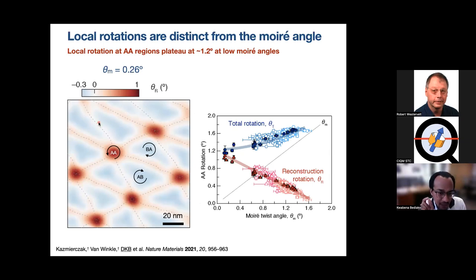But why does the rate plateau as you go below 1.5? Well, it turns out that we know that because of relaxation, the total rotation, if you were to put blinders on and only look at the rotation at an AA site, you would see from our measurements that the total rotation basically plateaus off. So even though the Moiré twist is 0.26 degrees, locally at an AA site, it looks like 1.2 degrees.